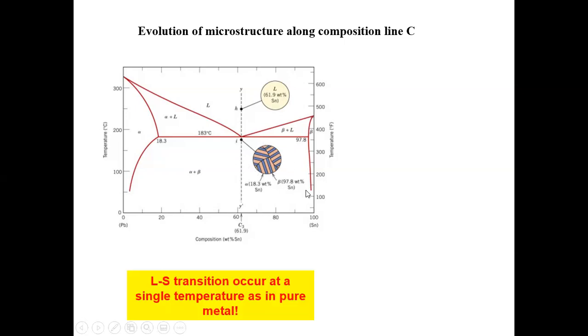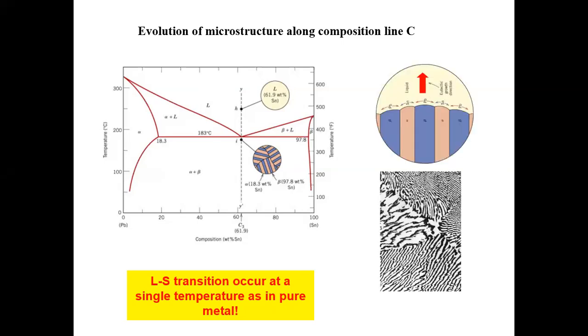Okay, so this transformation. In this eutectic system, there is this unique point, which we call the eutectic transformation. The reason is that it's a well-defined transformation at a single temperature, like in a pure metal, right? So we call this the eutectic transformation. We'll spend a little bit more time later to investigate the diffusion and how this occurs, nucleation, etc. But for here, I just want to quickly mention that the eutectic transformation occurs very quickly, right? This is distinctly different from the nucleation and transformation that you have for growing an alpha phase like this, right?